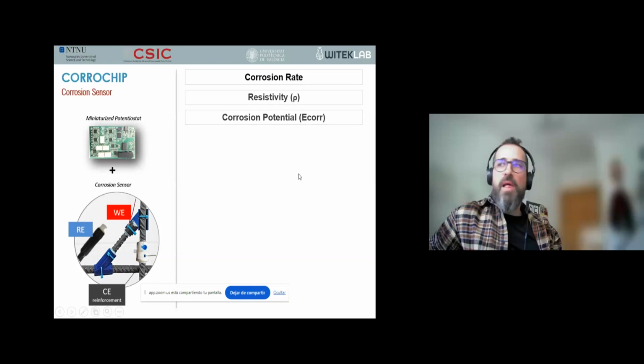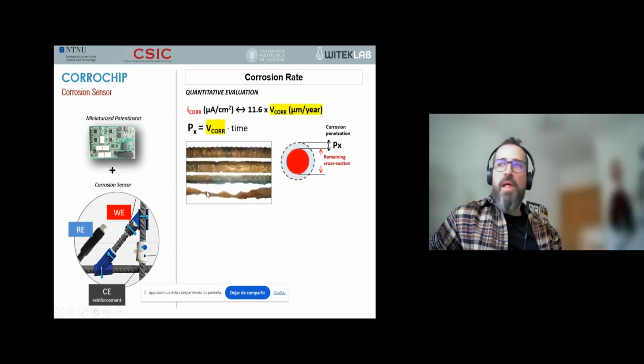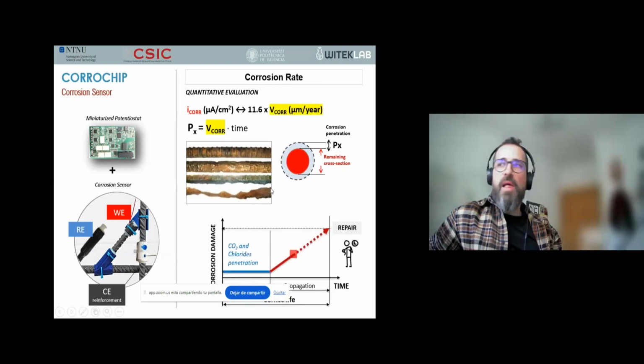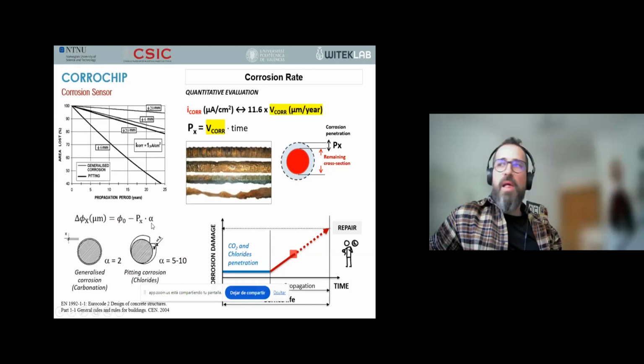As we have already seen, the rate is a quantitative parameter, as it allows us to determine reinforcement section loss. In fact, it's the parameter used in the various service life prediction models, some specifically when analyzing the propagation period, that's the period after the reinforcement depassivation until the end of the service life. For example, the European standard Eurocode 2 proposes a model to estimate the reinforcement section reduction considering a pitting factor, whose value depends on the type of attack: 2 for generalized corrosion, and between 5 and 10 for pitting corrosion by chlorides.